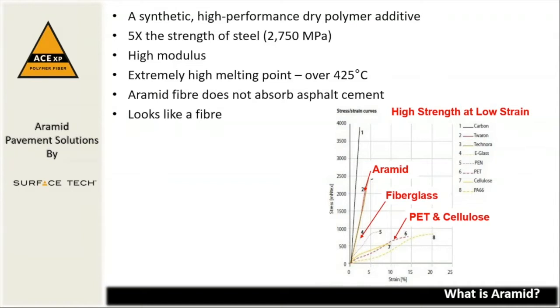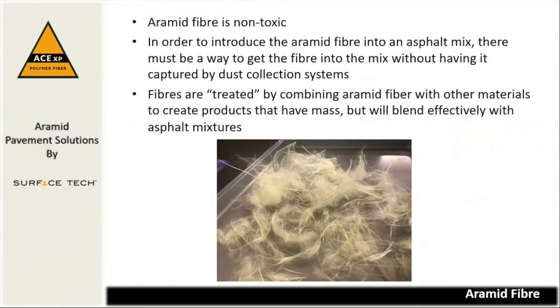The high temperatures required for asphalt production are well below the melting temperature of Aramid. Unlike cellulose fiber, Aramid does not absorb asphalt cement. Aramid is a non-toxic material that is very lightweight. In some applications, Aramid is used to replace asbestos because of that. In order to prevent the Aramid from floating on air currents and being sucked into a dust collection system, it must be treated with a material that will provide mass to the Aramid, but is also compatible with asphalt cement.